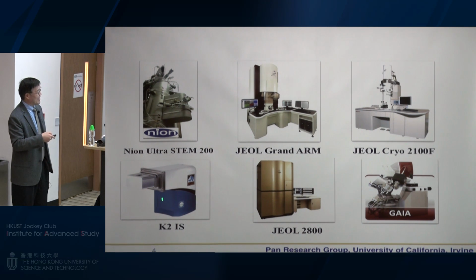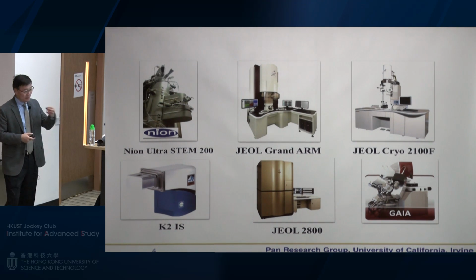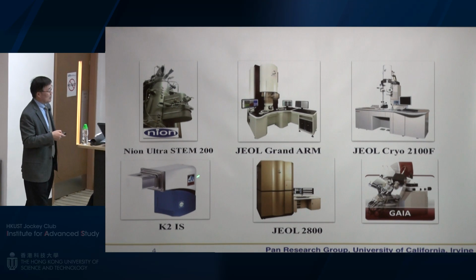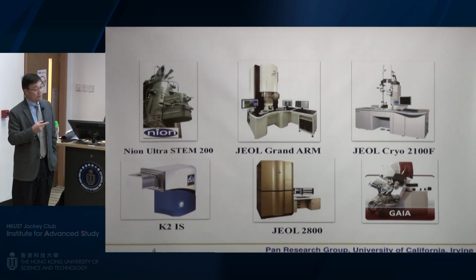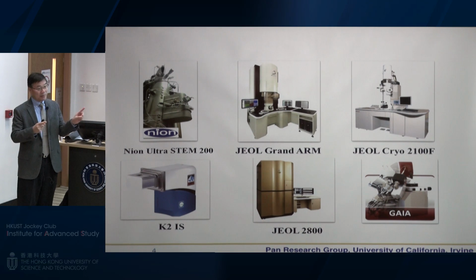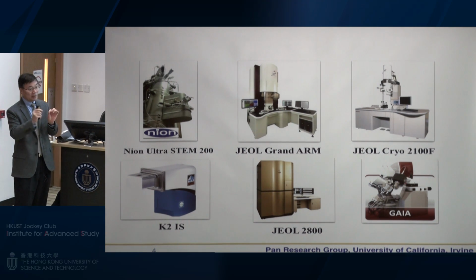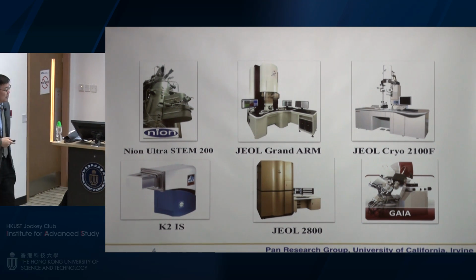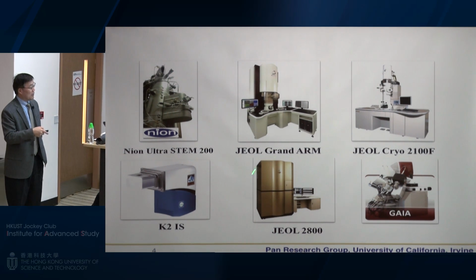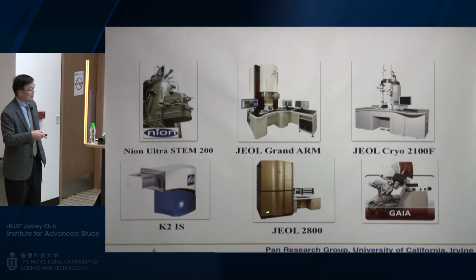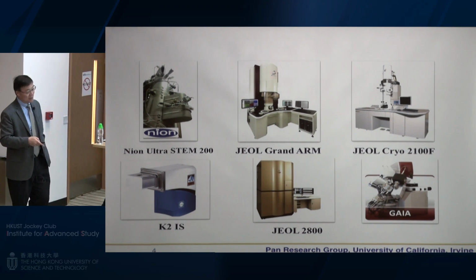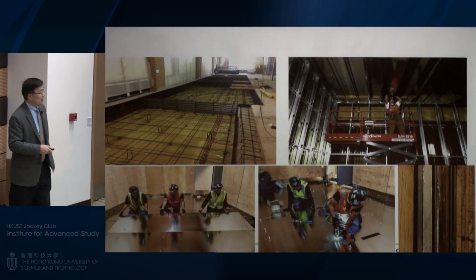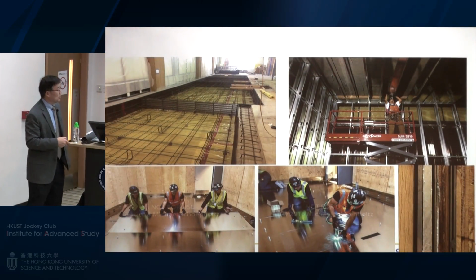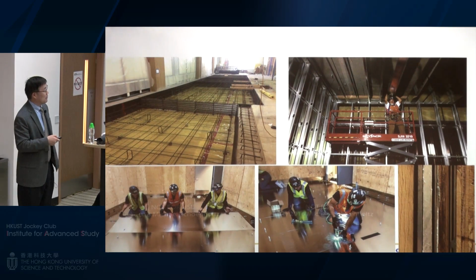And we also have an in-situ direct electron camera that will allow you to record the dynamic change in the microscope. You can record up to 1,600 frames per second. Each frame is a high-resolution image, not like a blurred individual frame in a regular video. And then we have a workhorse 200 kV transmission electron microscope and also STEM, and have a new FIB. So this was one of the initiatives launched by Irvine recently.